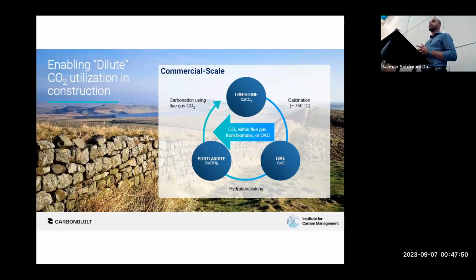So the idea around CO2 utilization is how do you maintain CO2 within the same loop? And the idea is pretty simple. You start with limestone, you burn it, you make calcium oxide. You go from calcium oxide, you slake it to produce calcium hydroxide. You carbonate calcium hydroxide and you go back to limestone, right? So limestone is essentially nature's original cementation agent. Can you use it for cementation was really the question to ask.